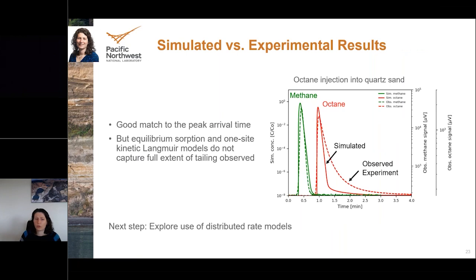So here are some initial results that we have of the simulated versus experimental conditions. This plot on the right shows the simulated results, which are solid lines, compared to the observed inverse GC experiment results, which are the dashed lines. The methane peak is shown in green. That's the quote-unquote inert gas in the inverse GC experiment that's assumed to not interact much with the solid material. There is some interaction, but not much. And then the octane, that's the probe gas.